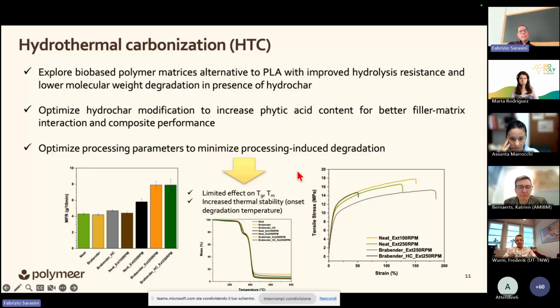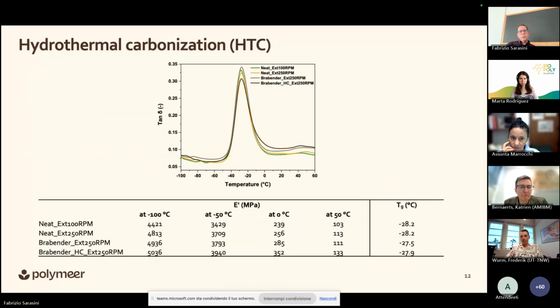At the same point, we didn't detect a significant effect on glass transition temperature and on melting temperature of this blend. And this was also associated with an increase, this time, in thermal stability. And if we look at the tensile stress strain curves, you can detect that there is a decrease in the tensile strength, but this time is much more severe compared to the previous case. And this is also supported by, for instance, DMA analysis. As you can see, the glass transition temperature was largely unaffected by the presence of this hydrochar.